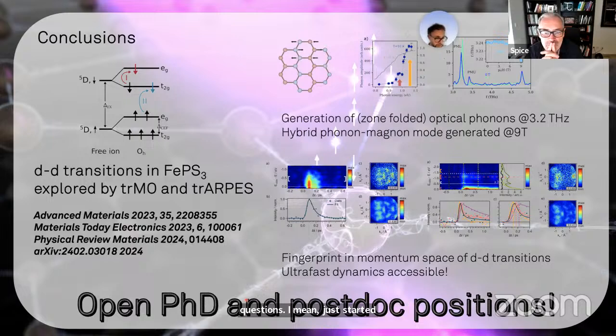I may just start it off a little bit from the point of view of this control aspect that you were mentioning. So in the fast relaxation, the fast spectroscopy that you're having in there, are you able to control the particle densities at different energy scales well and understand how the decay process is, and then control it through strain, or is it just at the moment more spectroscopy-wise? Well, I mean, control in this case is, as you can see here, you can basically control the amplitude of the phonon mode by just selecting the proper photon energy. Okay. This was, in this case, what we have achieved in terms of control.